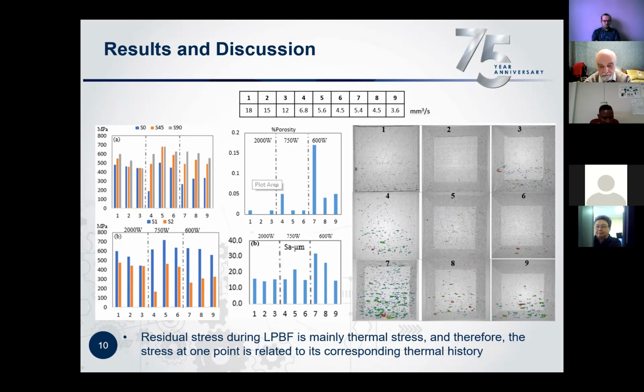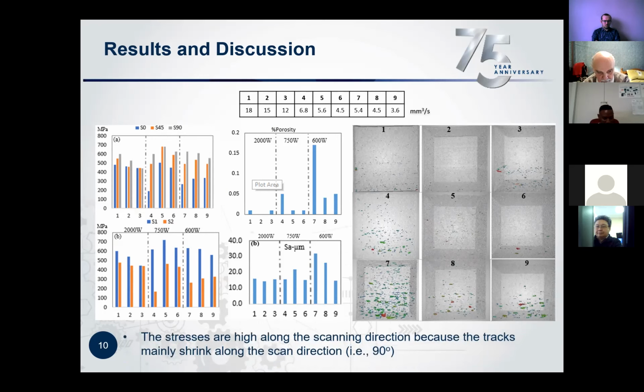One thing that we know about the residual stresses in LPBF is that it's mainly thermal stress, and therefore the stress at one point is related to its corresponding thermal history. The stresses are high along the scan direction because the tracks mainly shrink along the scan direction. This can be seen as S90 in our stress graphs. S90 represents your scan direction.